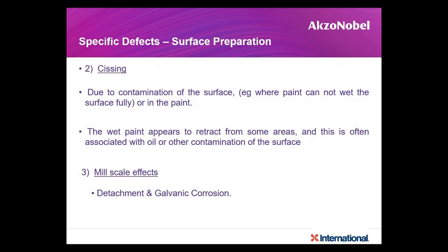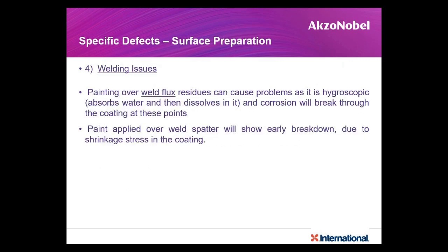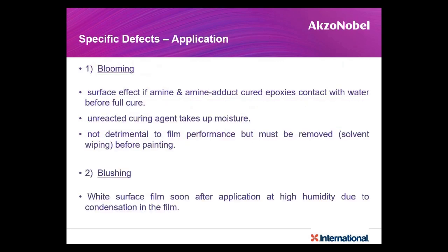Then mill scale effects. For example, when steel is exposed to a high temperature, it forms a bluish black oxide, which is mill scale. Mill scale is non-metallic, it can crack. So that detachment will lead to galvanic corrosion. It will lead to delamination. Keep in mind. Welding issues: I was talking to you about weld flux, stitch welding, weld spatter on steel. All these things need to be removed. If you apply paint on that, those areas will be loose. It will come out at a later date and start corroding.